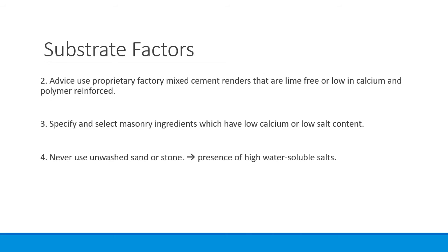Always use proprietary factory mixed cement render which is lime-free or low in calcium. Specifically select mortar ingredients which are low in calcium or salt content. Never use unwashed sand or stone. It could have a presence of high soluble salts.